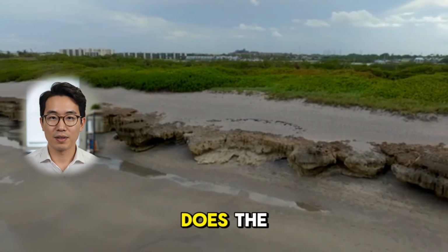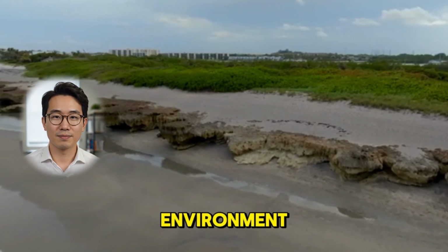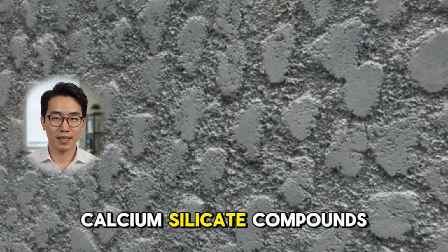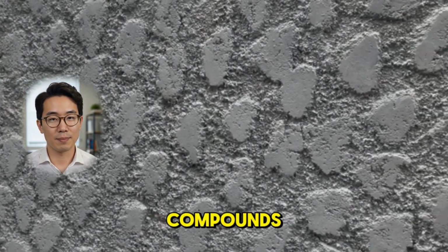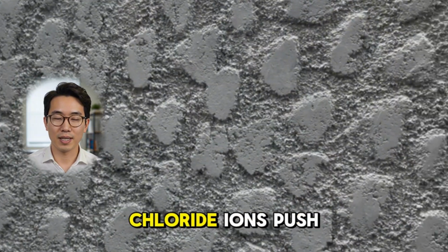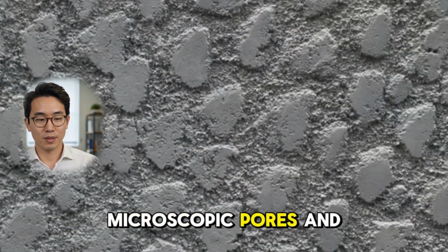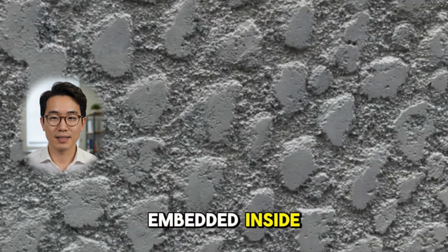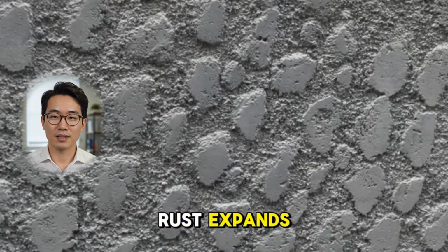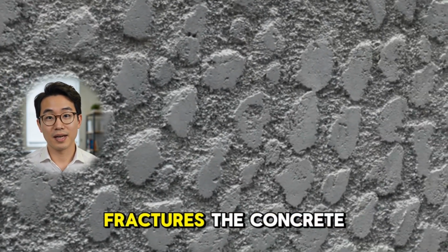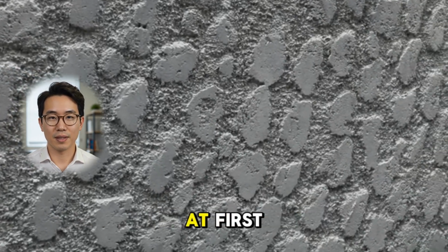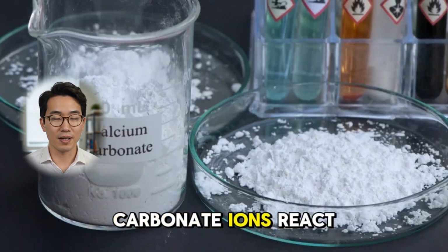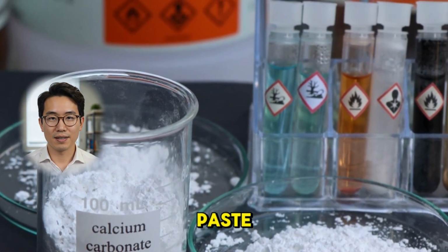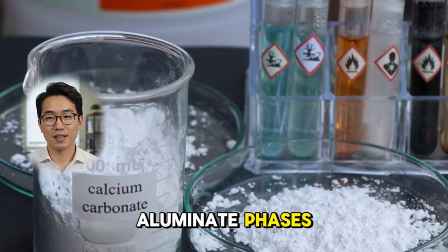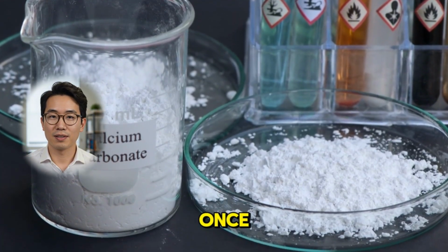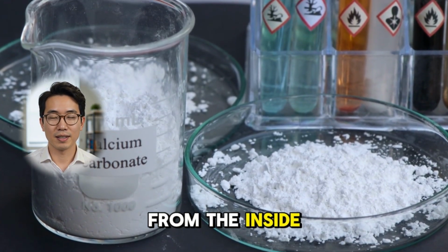Modern Portland cement does the exact opposite in the same environment. Portland cement is built around calcium silicate compounds. In seawater, those compounds are chemically unstable. Chloride ions push through the microscopic pores and reach the steel reinforcement embedded inside. The steel rusts. Rust expands. And that expansion fractures the concrete from within, invisibly at first, then catastrophically. Carbonate ions react with the calcium in the cement paste. Sulfates attack the aluminate phases. The structure does not fail all at once. It weakens steadily, invisibly, from the inside out.